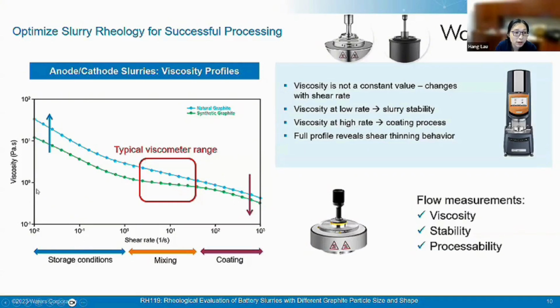In the low shearing region, you can understand your stability, your recovery region, what viscosity will recover after recoiling. Medium ranges often give you information on mixing. You understand certain shear rates during the mixing regime. And in high-speed coating, oftentimes you're going to ultra-high shearing. So you need to understand when you're under the high shearing regime, what the viscosity would be over those regions. A typical viscometer will give you a medium range, but you need to understand both low shearing and high shearing, helping you to dictate the process stability.